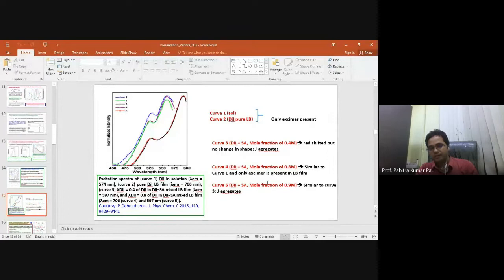So very interesting again. Only the excimeric band is present, because it is similar to this one, so it definitely should be the excimeric emission. So curve 5 is similar to curve 3. So you can compare these excitation spectroscopy results to the pure component. So you can conclude when the J aggregates are formed and when the excimeric bands are formed, and what is the range of the mole fraction and the transition between them.